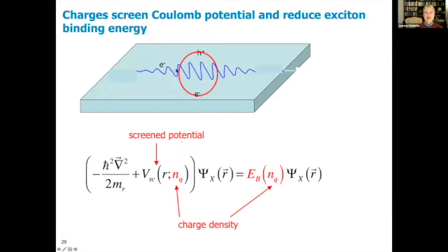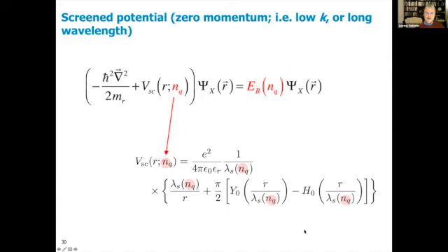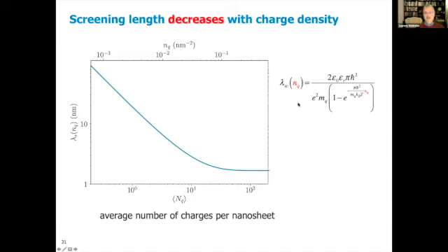So the idea is that a free electron, or electrons, could gather around the hole and screen the interaction with the other electron in an exciton, or you could say the electron moves in between the electron and the hole in an exciton. Now, the screened potential we took in the zero momentum or long wavelength limit, that's given by this expression. Lambda is a screening length, and here there is a Bessel function and a Struve function and so on. That's from literature. We took that expression, and then we calculated the screening length given by this expression as a function of the density of charges.